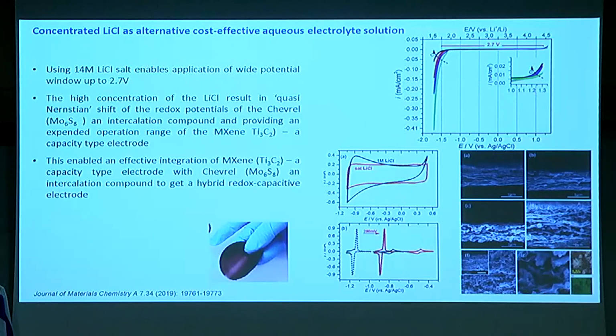So we decided to test this concentrated electrolyte for two systems. One is the MXene electrode, which is here. It has capacitive type response. You can see here the rectangular shape. And what you can see is that in 1 molar you have parasitic current in both negative and positive side. Here it's due to titanium oxidation. Here it's due to hydrogen formation. While in concentrated electrolyte you can get wide potential window without any significant parasitic reaction.